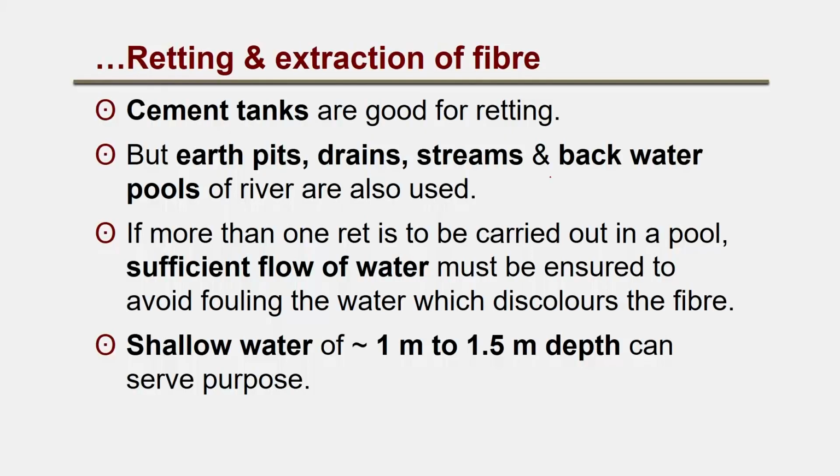But earth pits, drains, streams and backwater pools of river are also used. So, in certain cases these streams can be used, but the condition is that the flow of water should be less. If flow of water is very fast, then decomposition process may take longer time. If more than one ret is to be carried out in a pool, sufficient flow of water must be ensured to avoid fouling the water which discolors the fiber.